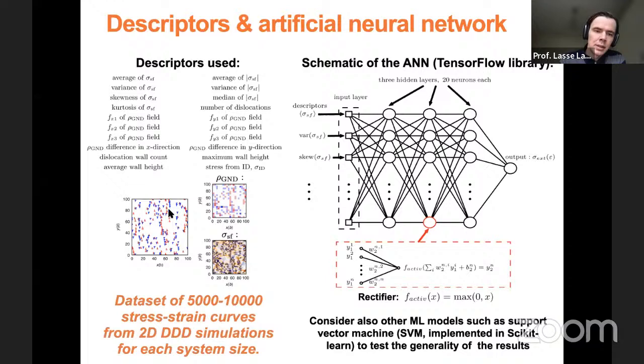And then from each of these initial configurations, you generate some descriptors. So these could be related to something called the geometric necessary dislocation density, which is basically just the difference of the densities of these positive and negative dislocations in your system. You could also look at some features of this internal stress field. That actually looks kind of complicated because you have all these dislocations forming this complex structure, and each of them is producing its own stress field. So the sum of those will look kind of nice and complicated. So then you can extract various statistical descriptors of those fields.